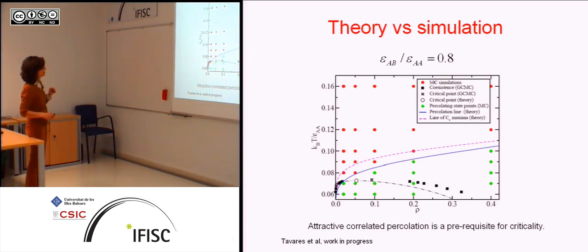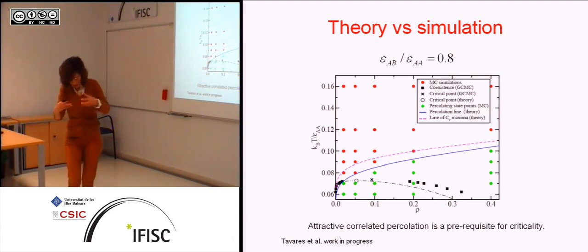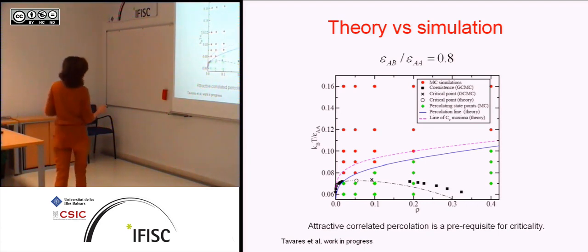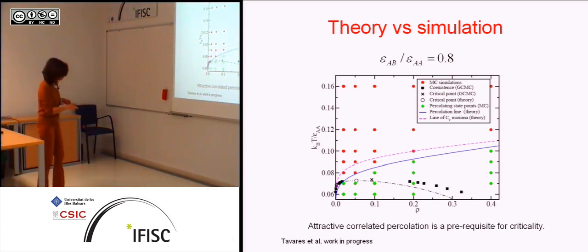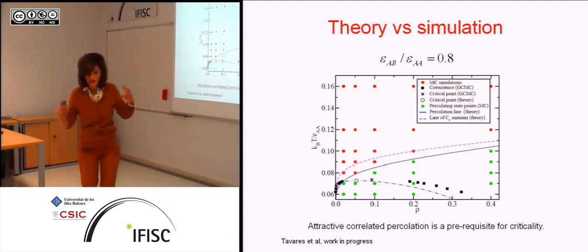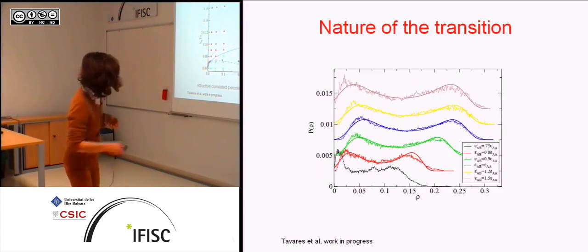And this is actually the percolation line that I showed you before, well, didn't show you before, but that Zemaria calculated. This is the maximum in the specific heat that will signal when these bonding processes are important. And what you see here, and answers the question that I was asking before, the critical point is here, the percolation line is on the left, so around the critical point we really have coexistence of two network fluids, two fluids that actually have giant clusters. They are in the percolated regime.